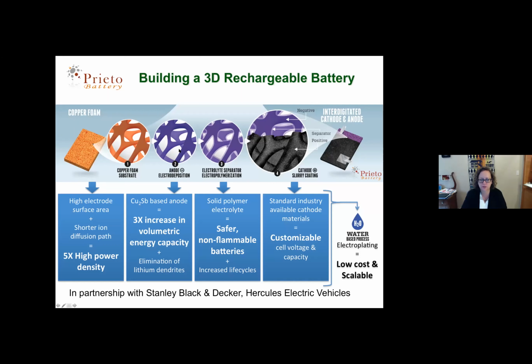This purple color I'm showing you in step 2 is copper antimonide. And a lot of the data that I'll show you today is from this compound. Copper antimonide is an unusual choice in a way. It is similar in terms of the conversion electrochemistry to silicon. It doesn't have as large of a theoretical gravimetric capacity as silicon, but it does have much higher electrical conductivity and much higher thermal conductivity. And more importantly, it lithiates at potentials more positive than the plating of lithium metal. So that's how we prevent, or in theory, inhibit lithium dendrite growth at high power conditions.